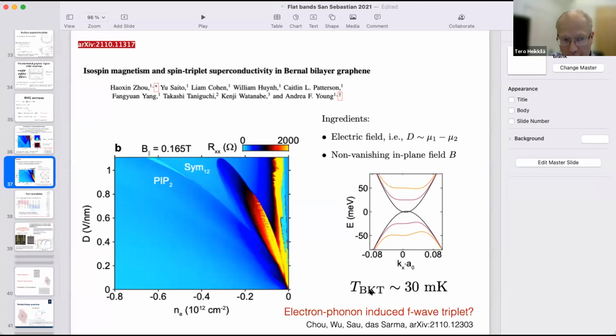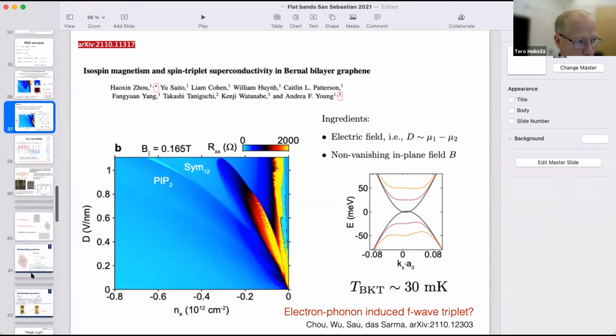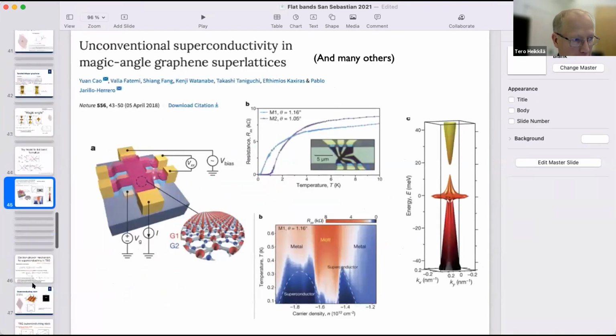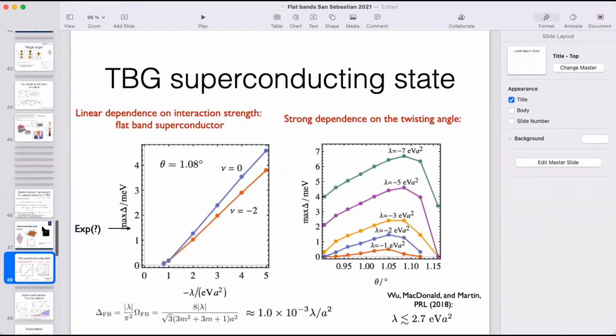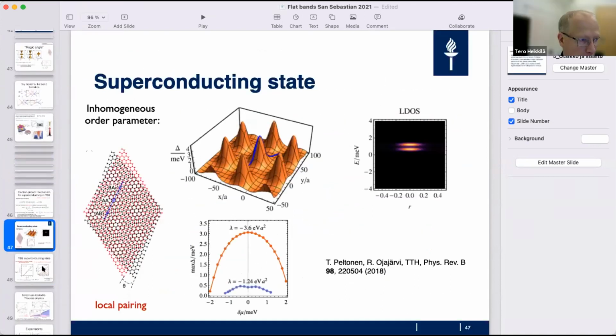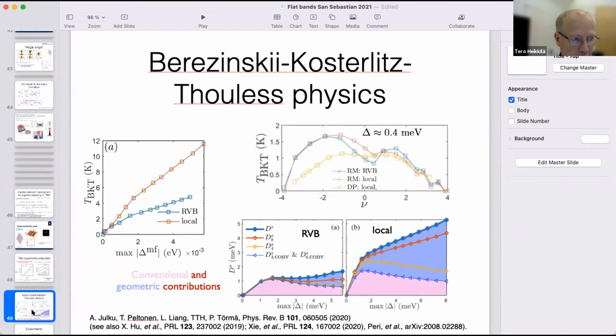So what you call T_BKT in your talk was essentially the mean field? No. One has to separate experiment from theory. In experiments they measure the BKT temperature. We have calculated both the mean field Tc, but also in the case of twisted bilayer graphene, we also calculate the BKT. Here everything is mean field, but then we use the mean field to calculate the superfluid weight. Then from the superfluid weight we can calculate the BKT temperature.